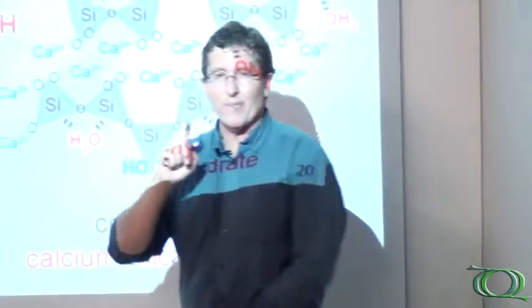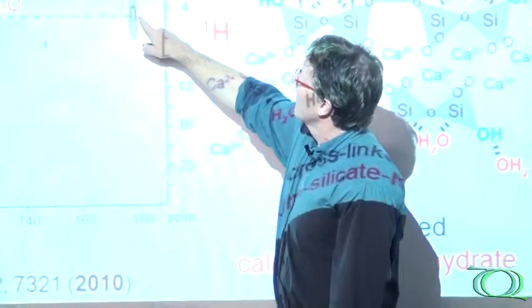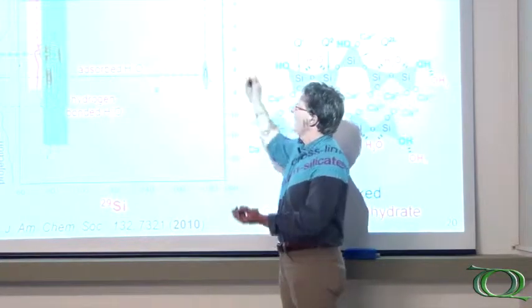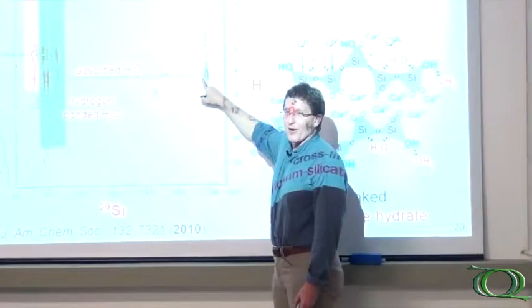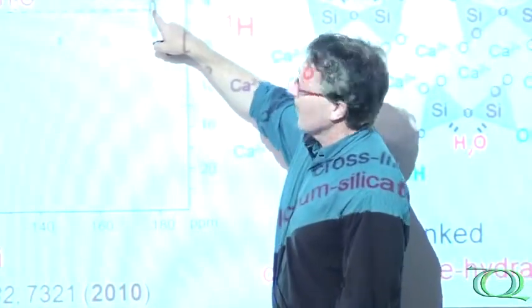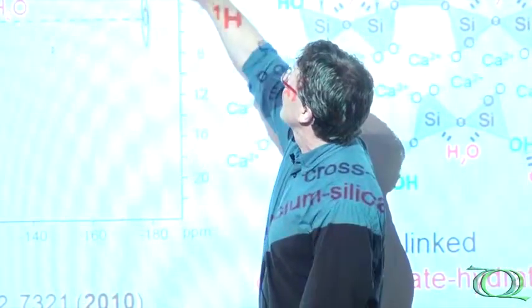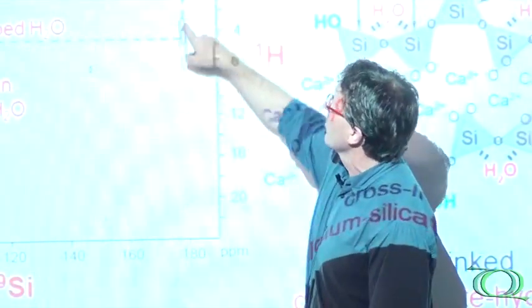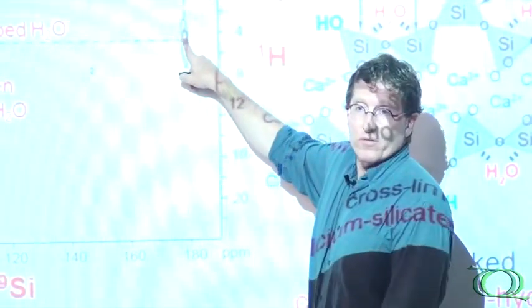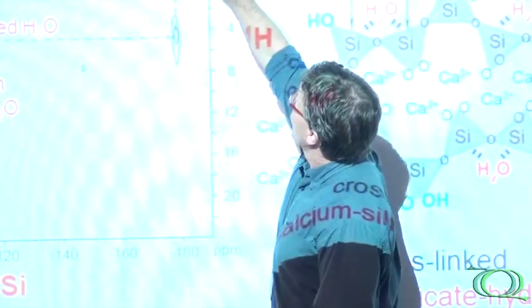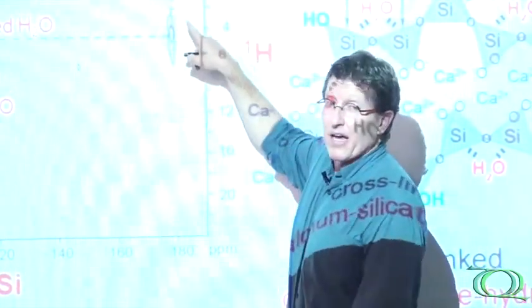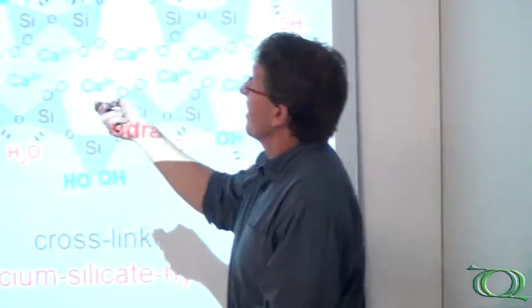And in case there's interest, I want to draw, especially maybe to Helmut's case, this we were really surprised about. If you look at this, I've never seen a signal in minus 179 ever before, and I thought this might have been an artifact or somehow a foldback from it, and I called Jonathan Stebbins at Stanford, who was a geologist, who basically guided me to some literature that established that this is actually six-coordinate silicon, which I never heard of before, but which actually exists in the form, this is a mineral thaumasite, it's a name for a German geologist from the 1920s or so, at six-coordinate silicon. And so, six-coordinate silicon is not a common feature to see in a spectrum of something that prefers to be four-coordinate. So this is really unusual to see a six-coordinate silicon, but there you go, and it's coordinated strongly to water.